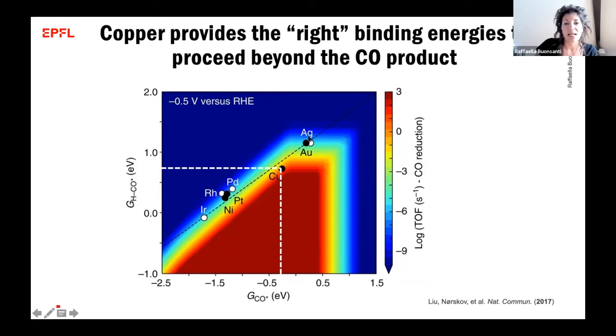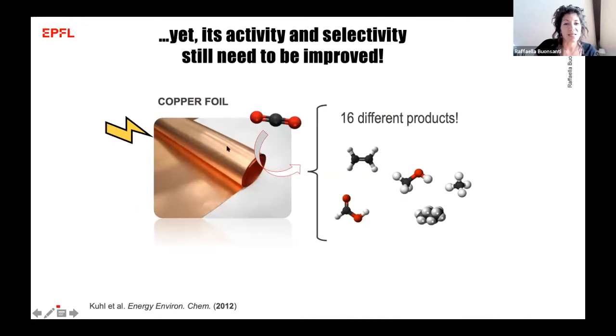So what we observe is that metals such as silver and gold don't bind CO too strongly. And so the CO2 is reduced up to CO, and then CO leaves the surface. So silver and gold are very good catalysts for CO production. Copper is special because it has this intermediate binding energy, which allows the reaction to proceed past CO. Other metals bind CO too strongly, and so eventually they get poisoned. Now, the problem is that if one takes copper foil, 16 different products are going to be produced, and this will be a separation nightmare.